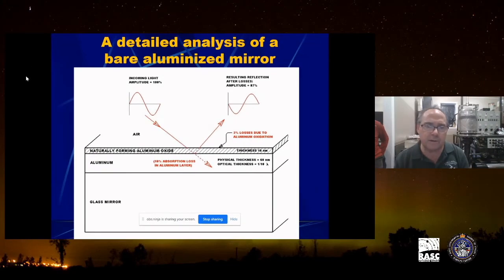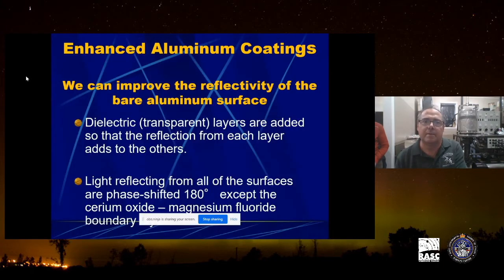Now, we used to use silver in the old days. Silver was 98, 99% reflective, but the problem with silver is that it tarnishes. It reacts with sulfur and forms silver sulfide, which is that ugly yellow appearance that you would see over the course of a year, especially if you lived in Sudbury. So, enhanced aluminum coatings, you've heard the term. All we're doing here is something similar to what we do with the lens. We're adding dielectric materials, but instead onto the aluminum.